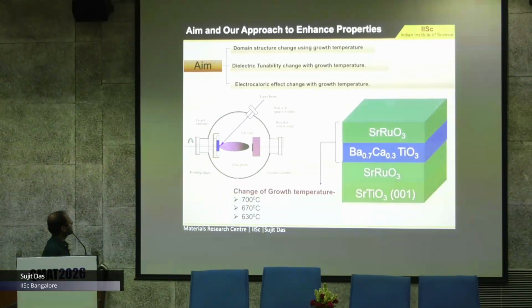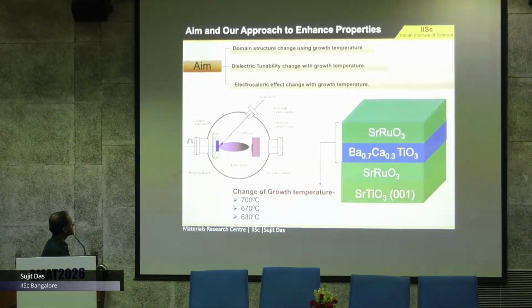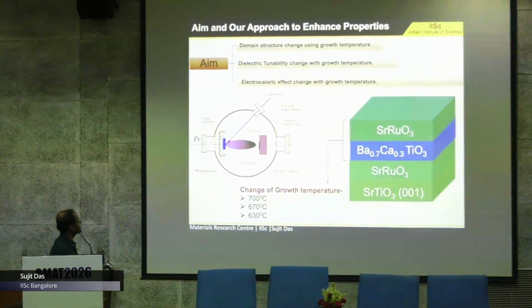We grow the materials under different growth conditions: 630 degrees C, 670 degrees C and 700 degrees C.